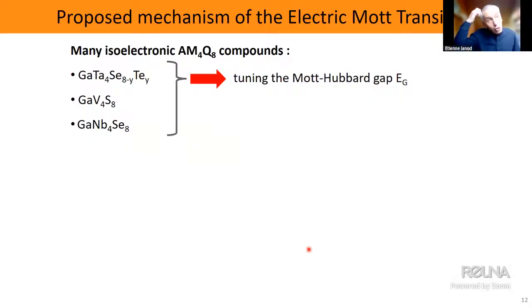In order to better understand the mechanism behind this, we have worked on the AM4Q8 system, and we have used the richness of the chemistry of this family. You see, we can change the metal, vanadium, niobium, tantalum, or we can change the chalcogen, sulfur, selenium, tellurium. And it's nice because it allows us to tune the value of the Mott-Hubbard gap.